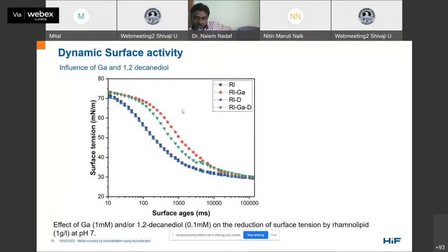Now looking at the influence of both gallium and 1,2-decanediol, we can see that if we add just 1,2-decanediol, it has no such effect as can be seen with the gallium. But when both gallium and 1,2-decanediol are present, again, it shifts the surface activity curve towards the right.